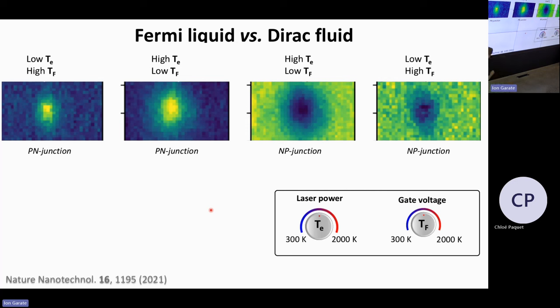And what you see is that both for the PN junction and the NP junction, if you're at low electron temperature and high Fermi temperature, you see a slightly smaller spot. If you, on the other side, are, where are we? Yeah, there we go. Here in the middle, you have a high electron temperature and a low Fermi temperature. So there you are in this Dirac fluid regime, and you see a larger blob. So the really nice thing is that I didn't do any normalization or scaling, because in both cases you get very similar magnitude of the signal.